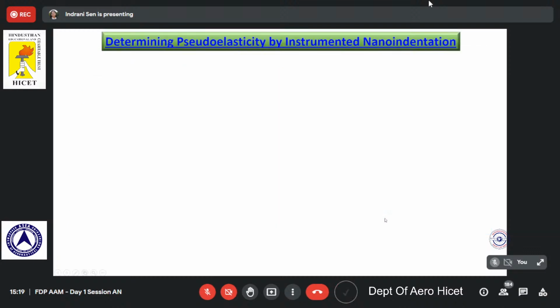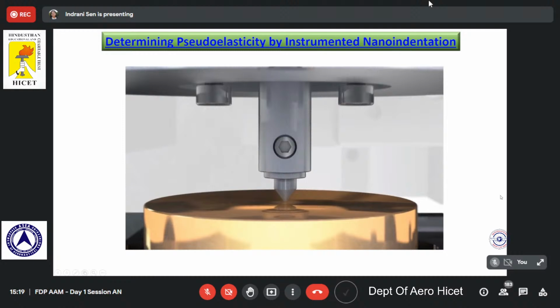Now, we tried to find out the pseudo-elasticity of each of these grains. Since the grains are very small, around 30-40 micrometers in size, we did indentation. As you can see in this small video, there is a specimen surface, and the indenter presses on it, and once it comes back, we get an impression of the indenter. Some part will be recovered and some part will be a permanent deformation. This is the force versus displacement, or depth of penetration, curve, where we force the indenter up to a certain level, and then when we are unloading, it does not come back to the initial position, but there is some elastic recovery and the rest is plastic.